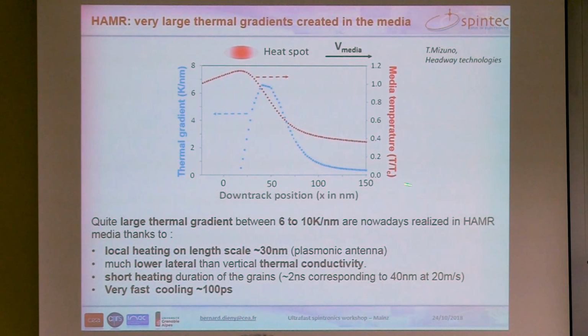So the horizontal scale can be viewed either as a snapshot of the temperature profile or as a time variation of temperature in a given grain. So a grain is warming up as it gets closer and closer to below the plasmonic antenna, and then after it cools down quite quickly. And you see that here the blue curve is actually the thermal gradient. We can achieve thermal gradient of the order of 7 Kelvin to 10 Kelvin per nanometer.